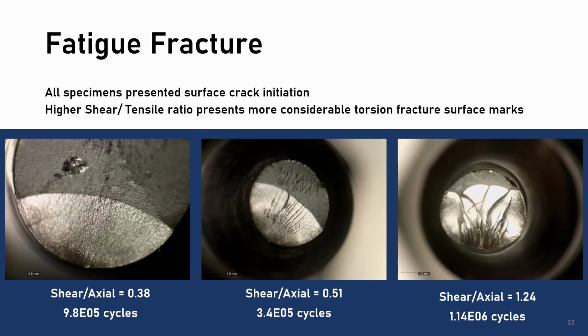Now, several tension-torsion specimens were tested with different shear and axial ratios. All tested specimens presented surface crack initiation, and the higher the shear tensile ratio, the more considerable the torsion fracture surface marks we can see. We can clearly see for a considerable shear and axial ratio marks associated with shear damage, much more pronounced than when the axial tension is much higher than the shear tension.